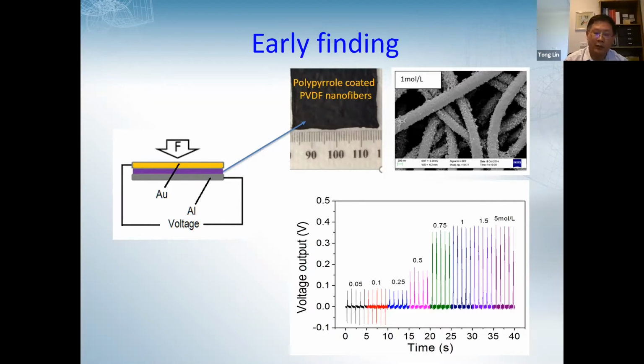Because this material is not conductive, it has a large internal resistance. To reduce that, we tried to use a conducting polymer to improve the conductivity. We used a solution to synthesize the conducting polymer, and in the meantime added nanofibers in the solution. By changing the concentration of pyrrole, we found the coated nanofiber can have different output. For example, for low loading of PPy, we still have an AC power output. However, when the loading is high, the power becomes DC.